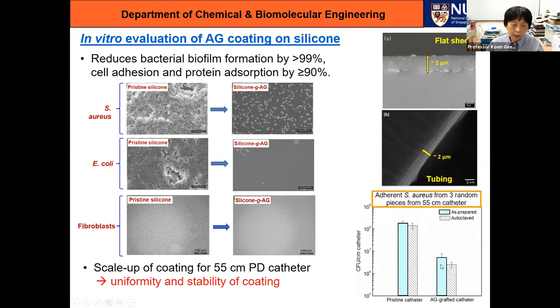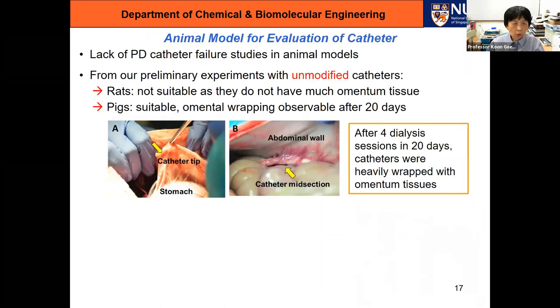The other thing we need to test is how stable this coating is. So we put it into the autoclave before the antimicrobial assay and then carry out the assay. The second bar, the one with the slanting lines, is after autoclaving. There's no significant difference between before and after autoclaving. That means the catheter coating is stable. So we want to proceed to an animal model.